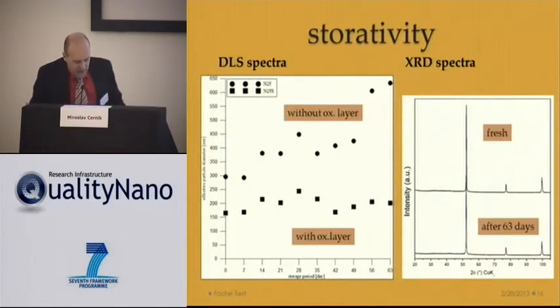The other parameter is the storativity. We need to have particles which survive for some period of time, and here we have two examples, the particles without and with this oxidic layer, and this is DLS spectra showing that the mean particle diameter is more or less constant with the surface, with this oxidic layer.